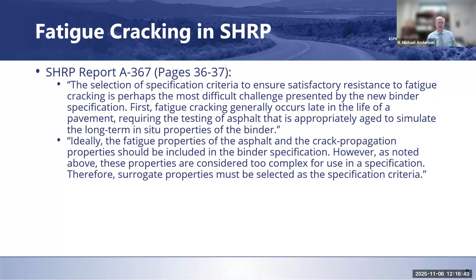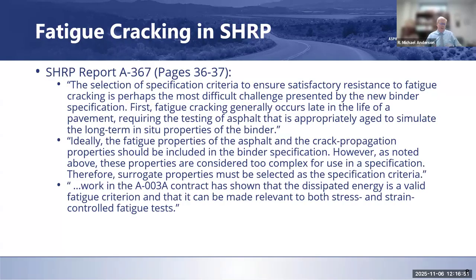What they ended up looking at was dissipated energy. And they found that that was a valid fatigue criterion, and that's related to the viscous component of the modulus that seemed to be relevant to fatigue in both strain-controlled and stress-controlled pavements. And so they recognized that you couldn't really put thickness into it, but you could pick a surrogate parameter that would capture both of those things. And that was this dissipated energy concept.